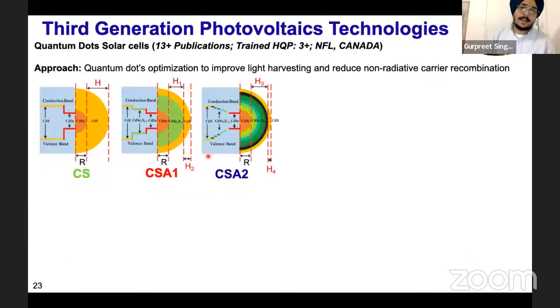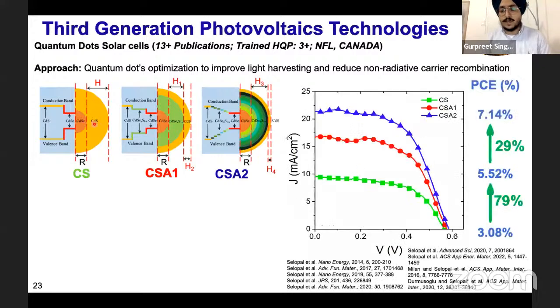So at INRS, we are trying to minimize these non-radiative recombinations by exploring the core-shell nanoengineering approach. In the first phase, we cover the core of the quantum dot with a shell of a different material, in this case cadmium selenide as the core and cadmium sulfide as the shell. And by doing so, you can see we move from 3% to 5%.